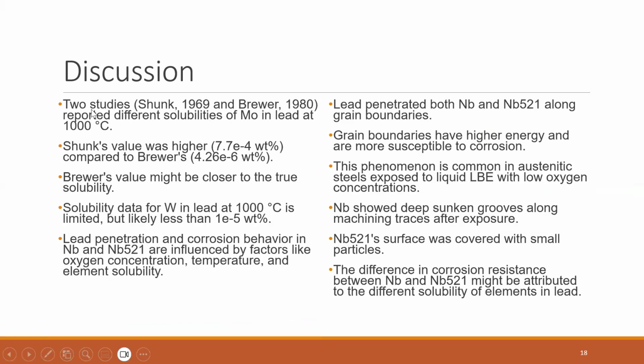And in two studies, Shunk and Brewer reported different solubilities of molybdenum in lead at 1000 degrees Celsius. Shunk's value was higher compared to Brewer's, and Brewer's value might be closer to the true solubility. Solubility data for tungsten in lead at 1000 degrees Celsius is limited, but likely less than this value. And lead penetration and corrosion behavior in niobium and niobium alloy are influenced by factors like oxygen concentration, temperature, and element solubility.